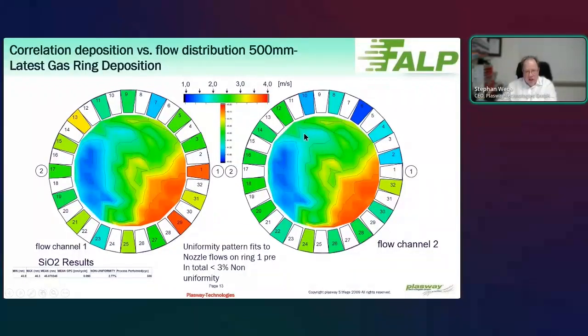What is also very important for us is to have a clear indication of the performance before we bring this gas ring into the chamber. Here you see, for example, a uniformity map. In this case, we achieved all in all 3% uniformity of SiO2 deposition, but you see already 2 of these nozzles were not so good with respect to the overall mean value. With the measurement of a direct flow of each gas, we have a very good possibility for a quality check of the gas ring. And we are even able to test each segment before any debinding, etc.